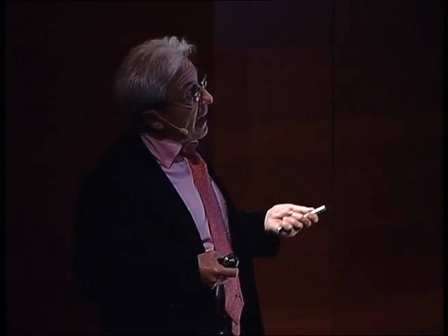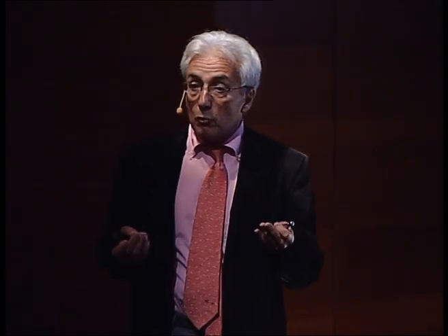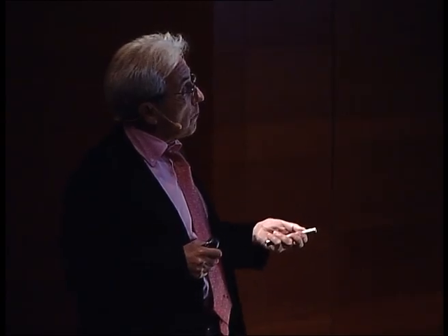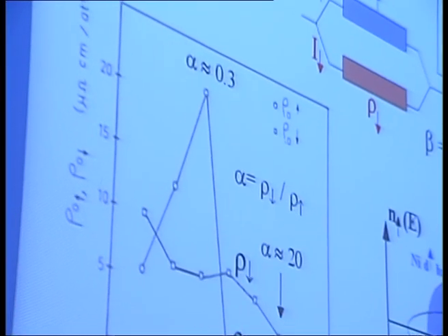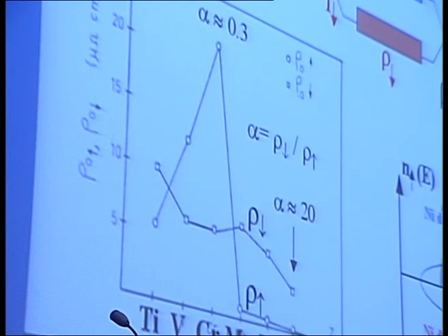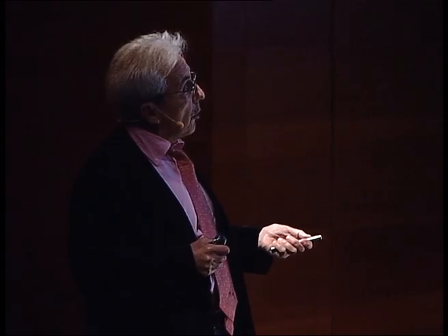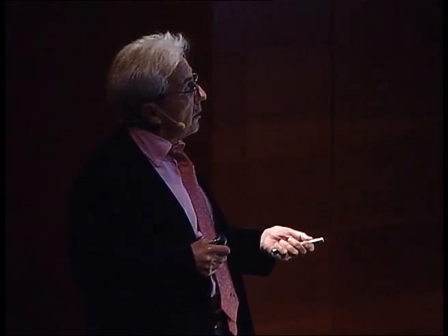spin down, and the contrast between the conductivity of the two channels can be very large, especially when one dopes the material with impurity, also introducing strongly spin-dependent scattering cross-sections. For example, you can see the resistivity of the two channels up and down introduced by 1% of several types of impurity in nickel. You can see, for example, if you dope nickel with cobalt, the resistivity of the spin down channel is 20 times larger than the resistivity of spin up, and this is the contrary, for example, for chromium or vanadium.